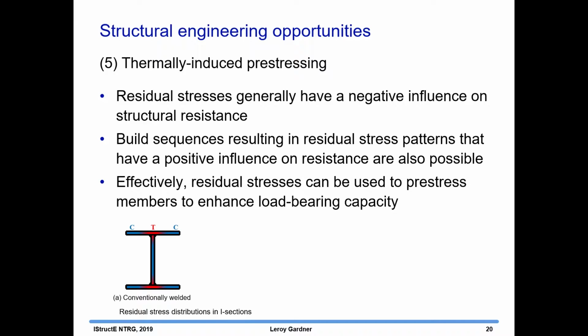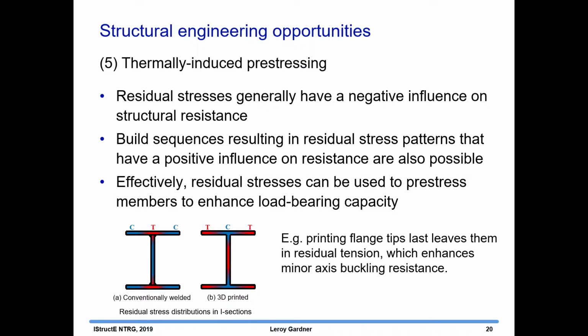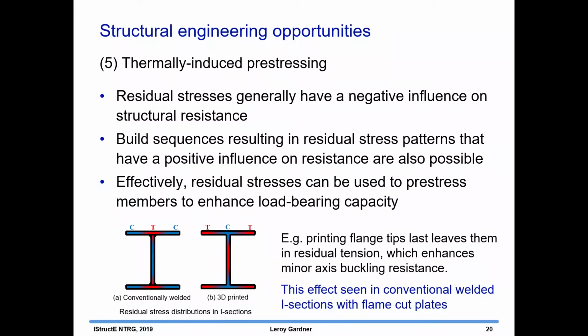An example of that would be, this is a conventional I section which has been welded at the flange to web junction, and that puts the tips of the flanges in compression. And in terms of your minor axis buckling resistance, that compression reduces your capacity. If you 3D print the section and you 3D print the tips last, that will leave them in residual tension, and that could potentially enhance the flexural buckling resistance. And we already see this effect in conventionally welded I sections which have flame-cut plates, which give you these tensile residual stresses at the flange tips.